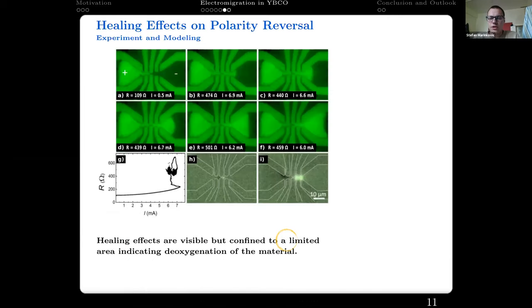We have also further investigated if it is possible to heal films by switching the polarity of the effect. And for that, we also performed optical imaging. There's also a video available in the supplementary material, which is published. As you can see, there is again a propagating front on the other side. Now the polarity is switched and the cathode is on the right side. But we do not effectively see much healing. What we see is a new propagating front going towards the right.